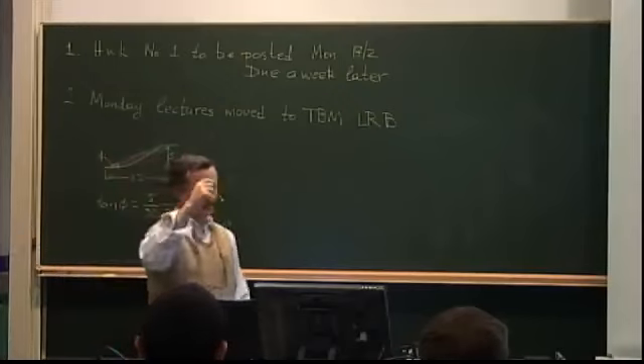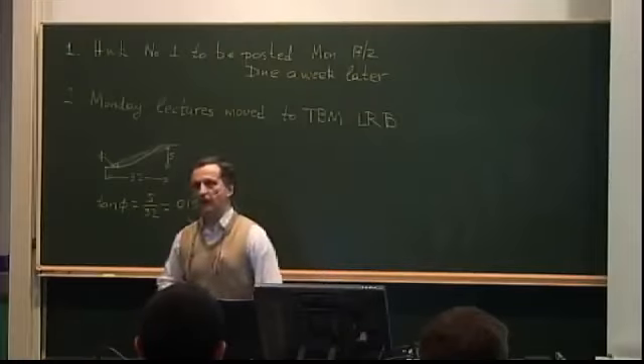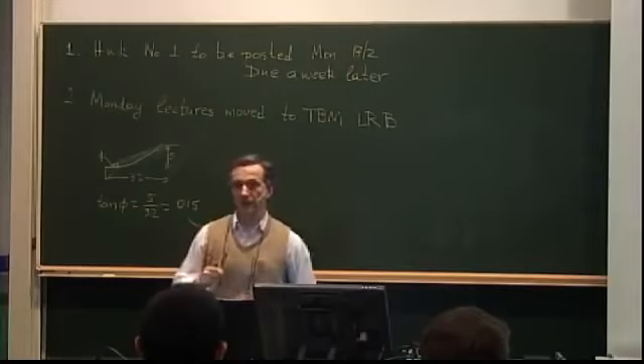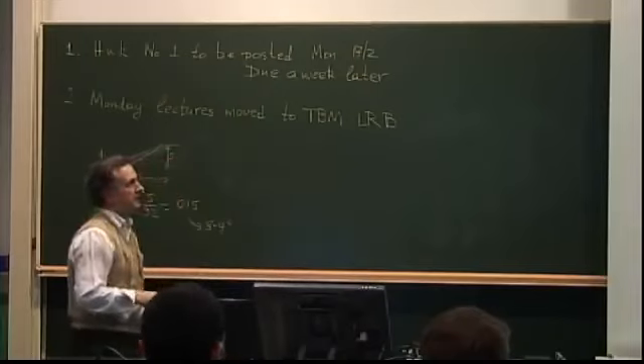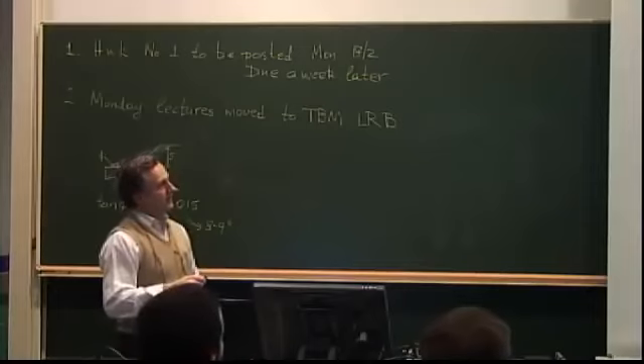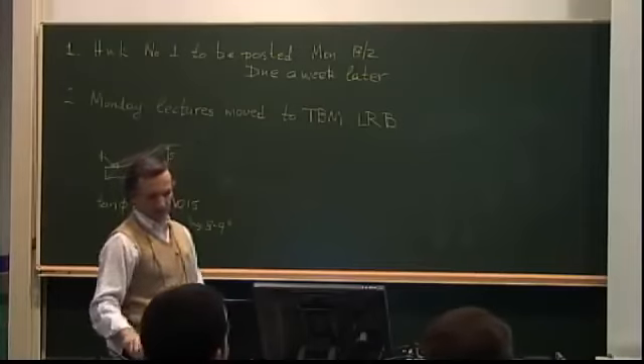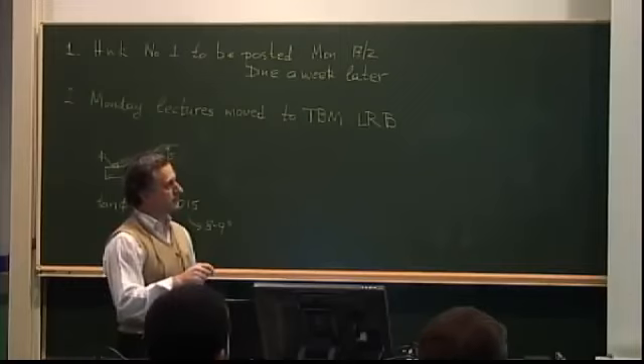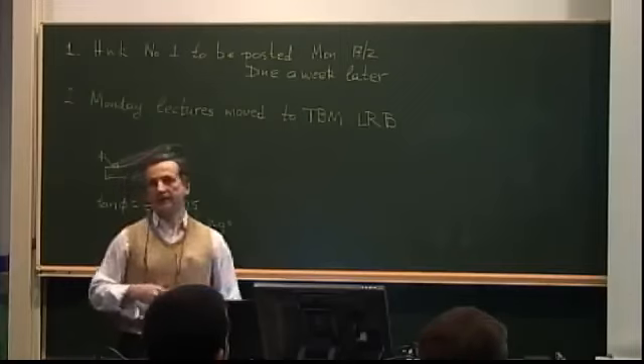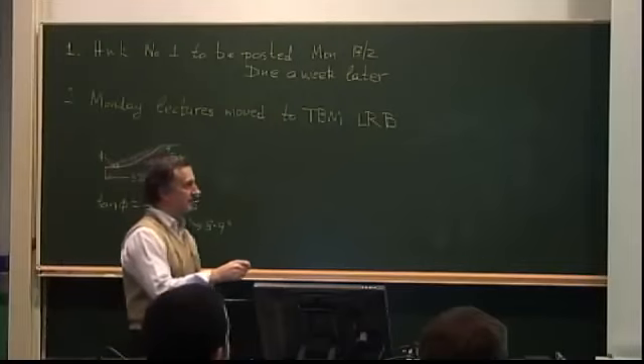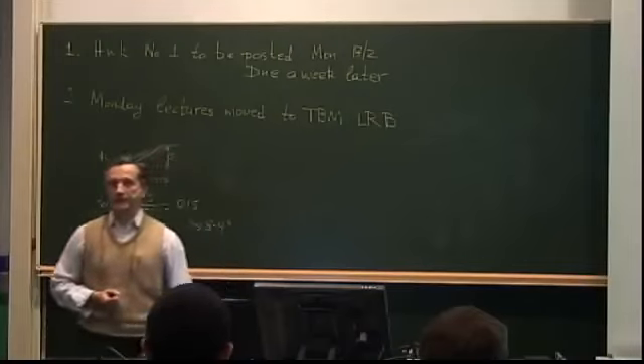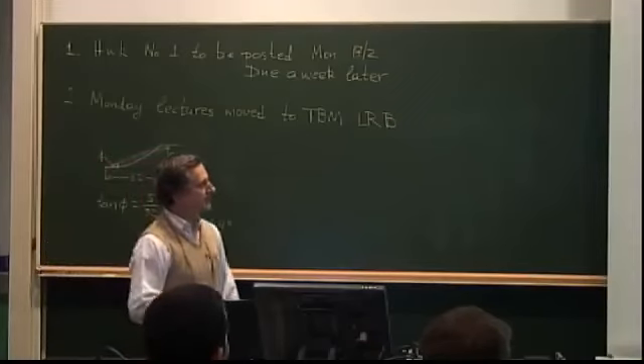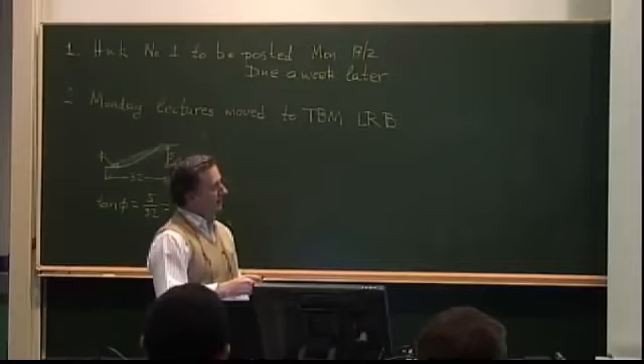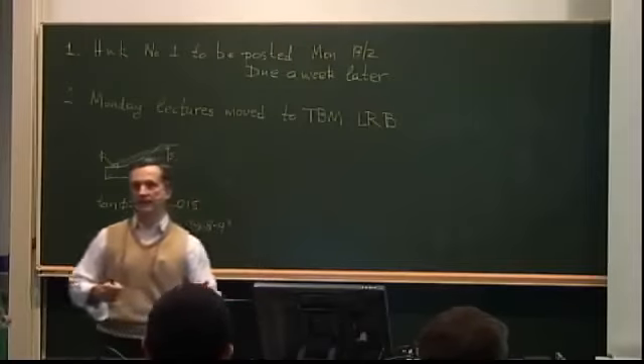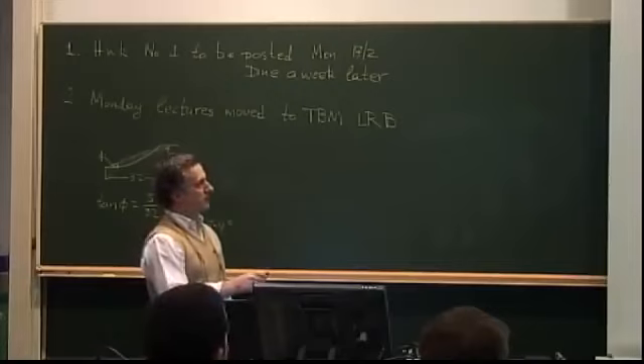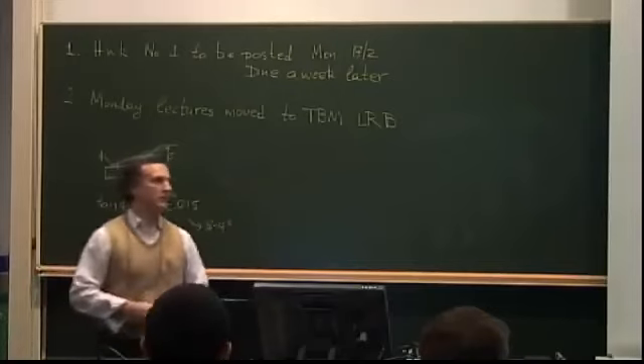In metals, the tensile yield and compressive yield for most alloys of aluminum, let's say, are reasonably close, within a few percent. Here, they can be off by more than 30%. Similarly, if you have loading in the Y direction, perpendicular to the fibers, then you would use the tensile or compressive strength perpendicular to the fibers. And again, if the applied stress exceeds the allowable strength of the material, then you have failure. And finally, you would have the shear. I put the absolute value because whether it's positive or negative, you just take its absolute value and compare it to the measured shear strength, and if it exceeds, then you are in trouble.